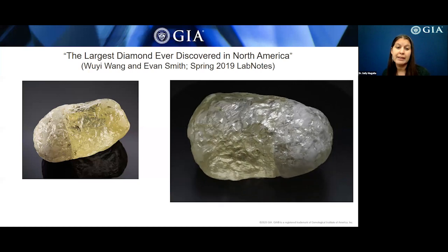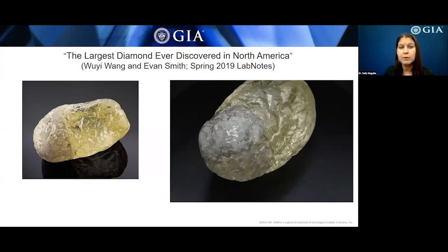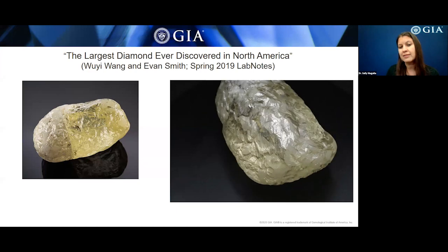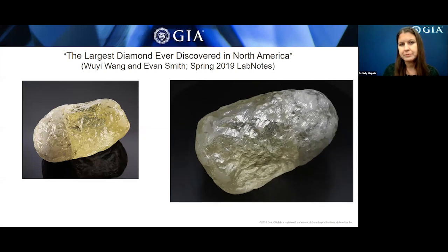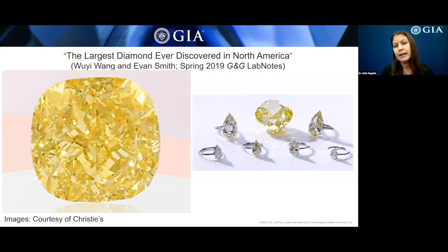Under long wave UV radiation, this diamond has strong blue fluorescence and weak but long-lasting yellow phosphorescence. And since that lab note was first published, the rough has been faceted. The primary faceted stone is a 204 carat yellow diamond called the Dancing Sun. It had a color grade of fancy intense yellow and a clarity grade of VVS2. Christie's also offered 6 satellite diamonds that were cut from what they called the 552.